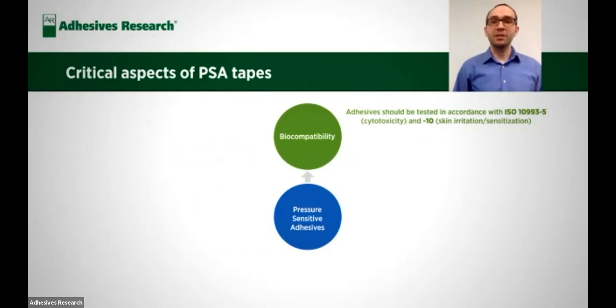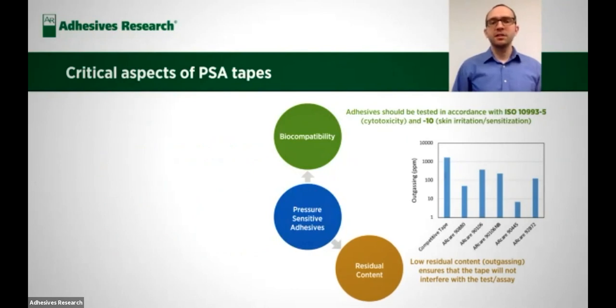The first would be the biocompatibility of the tape. Adhesives can be tested for their accordance with ISO 10993-5 and -10, cytotoxicity, skin irritation, skin sensitization, and that gives you an idea of whether the tape will support or interfere with biological activity. Related to that is the residual content in the adhesive. So after the adhesive is manufactured, it should have low residual content of volatile materials. And I show an example here of ARcare products, acrylic tapes, relative to a competitive tape, showing the low outgassing that we can achieve in our tapes by designing the process to produce them in a way that's going to